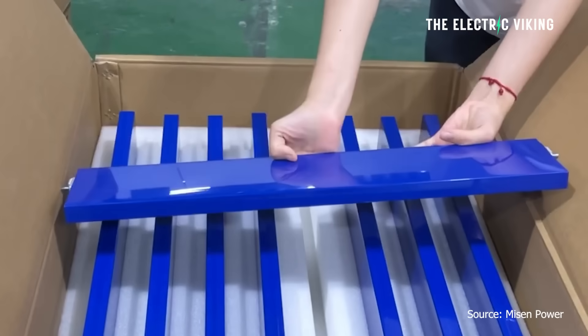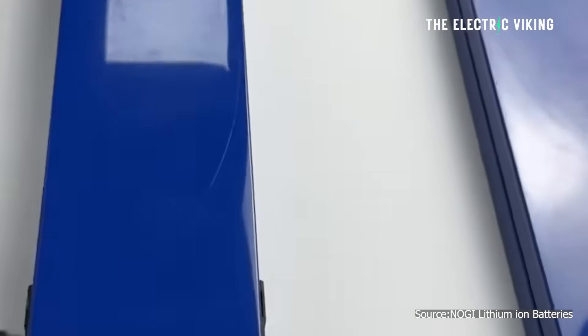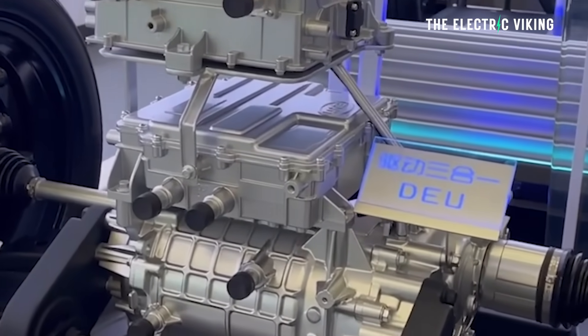S-Volt Energy is a Chinese battery company, a subsidiary of Great Wall Motors, and they've just unveiled this battery at their fifth battery day event in Chengdu. The Feng Xing short blade battery has a 6C charging multiplier and an energy density of 185 watt hours per kilogram. It's a lithium iron phosphate battery — not super high energy density in absolute terms, but very high for this type, since it's harder to achieve high energy density in short blade batteries.